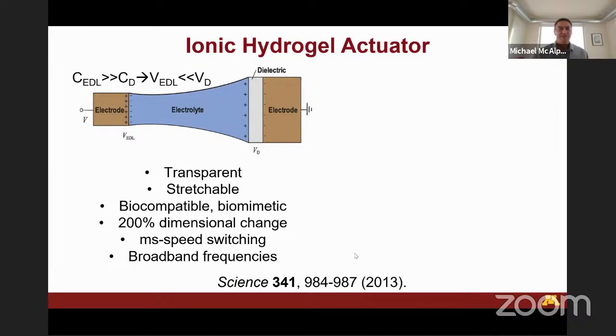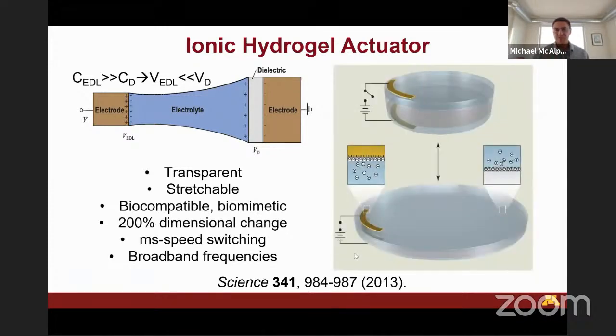But the point here is that the capacitance of that double layer at the electrode is much larger than the capacitance across the dielectric. So the voltage drop occurs across the dielectric, right? So you don't have issues with degrading your interface or the electrolyte. And Ziguang basically demonstrated this actuator where, by spreading ions across the sandwich, the ions attract, which forces it to compress and then stretch out due to Poisson ratio.